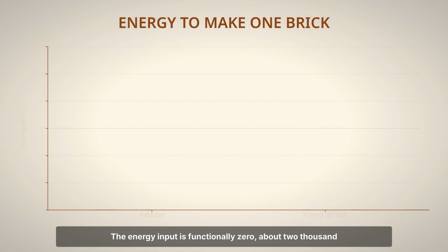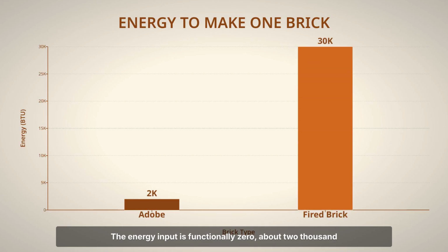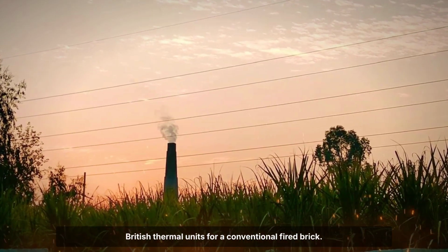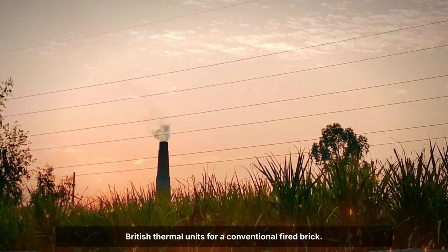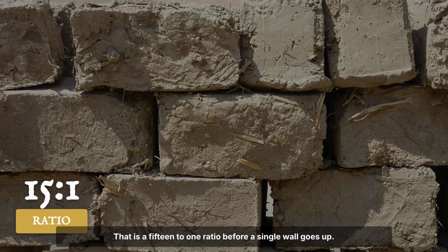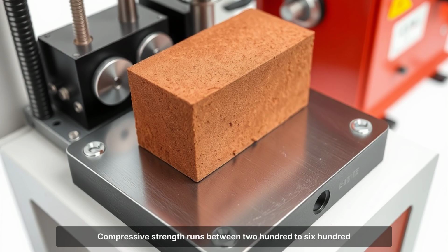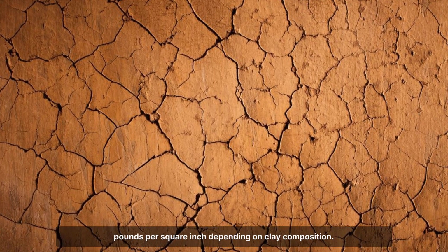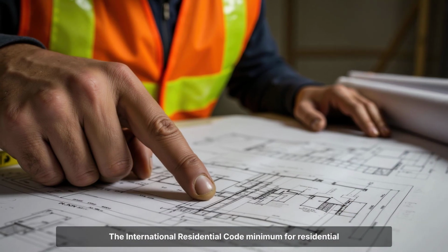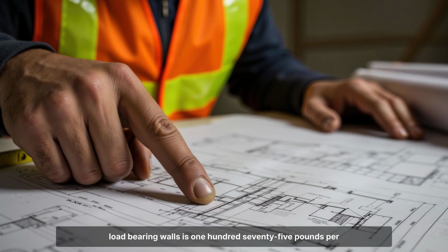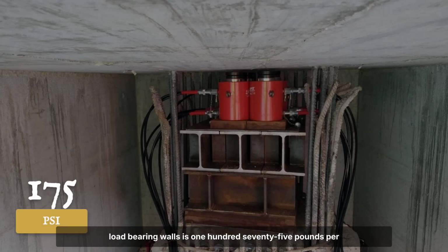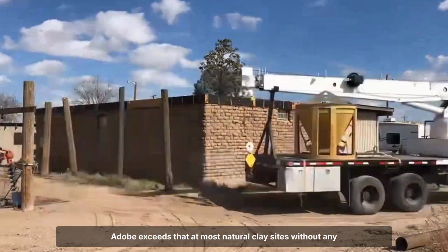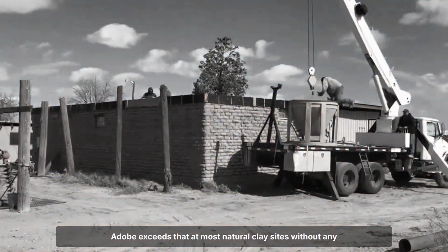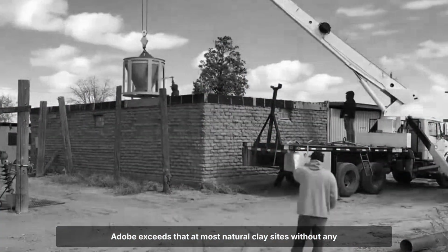The energy input is functionally zero, about 2,000 British thermal units per brick compared to 30,000 British thermal units for a conventional fired brick. That is a 15-to-1 ratio before a single wall goes up. Compressive strength runs between 200 to 600 pounds per square inch depending on clay composition. The International Residential Code minimum for residential load-bearing walls is 175 pounds per square inch. Adobe exceeds that at most natural clay sites without any modification.